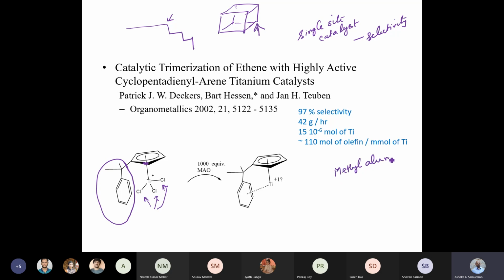Methyl alumoxane. And actually it is aluminum with oxygen and methyl in it. So it is a polymeric species, and its structure itself is heterogeneous, but the species it generates is supposedly something like this, where you have a titanium which is not coordinated. I'll tell you why it's not coordinated with anything else. So it's highly reactive. So these sites are available for coordination by the olefin.